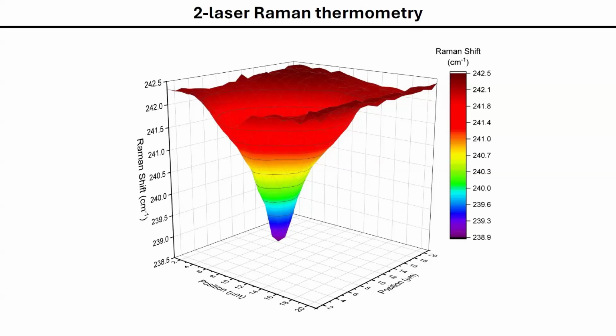But yes, there could be advantages, because in this case your probe laser is not hitting the sample, so you are just recovering this temperature profile. And with respect to the other, you are looking at the red shift of the peaks, but you can also look at the difference of intensity of the anti-Stokes and Stokes signals. I don't know if this technique is also widely used in this context, based on the intensities, or if you have more problems, or if you can comment a little bit on that.